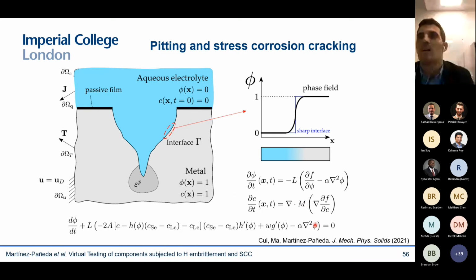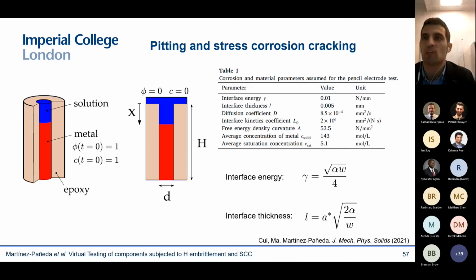And then you have the long range interactions, which you solve with an equation similar to Fick's law, where you basically calculate the diffusion of metal ions away from the interface. And as I said, I won't get into the details. You can find them in the paper, but everything is derived from the free energy based on thermodynamic principles and trying to be as physically sound as possible. And I will show a few examples. And what I want to show here is that the model can capture the main experimental trends. What I'm showing here is what they call the pencil electrode test. It's a classic corrosion benchmark.